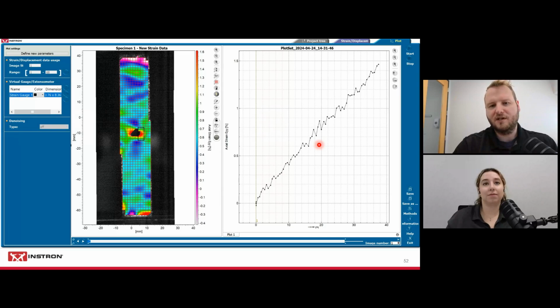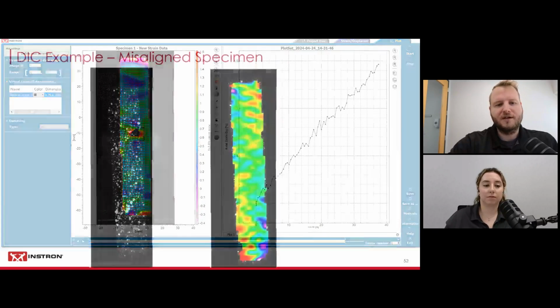So DIC is not an accepted technique in the standards yet, but it's definitely extremely helpful. And you can see the advantage right here. Instead of just having a localized strain measurement, which might not even be the highest strain region, with the DIC software you can see the highest strain regions and then apply strain gauges or extensometers manually. You can change the size of them and the location. Here I have one strain gauge simulated, and when you run through that test, this is the curve it generates and tells me your strain here is around 1.5%. That is a huge advantage of DIC.